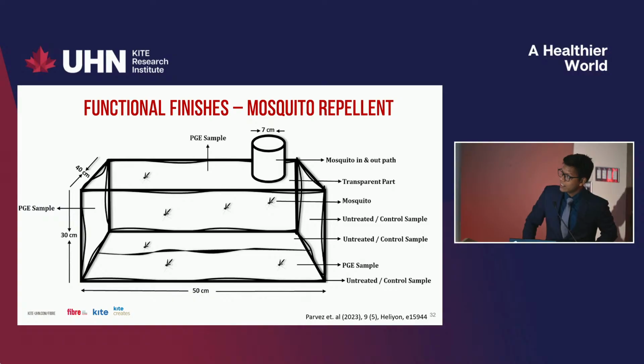We did another test. The result is also quite similar. The highest mortality rate we found was around 85%. Here is a modified cage test, but similar. We used our sample fabric on the walls of the cage. Also, we had some control fabric without the finish as well.